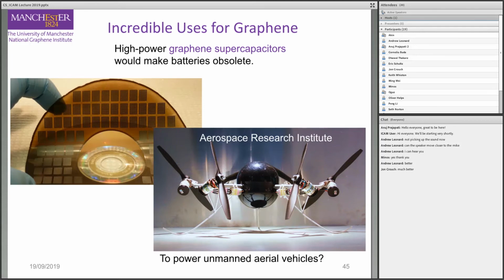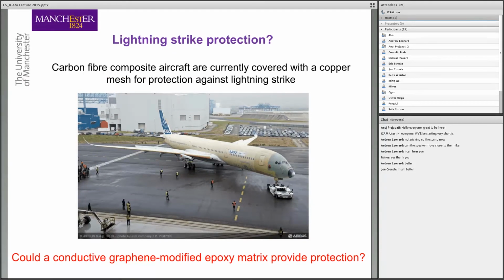And then we go back to those composite airframes like the Airbus A350 and the Boeing 787. Those structures, those carbon fiber composite aircrafts, are currently covered with a copper mesh for protection against lightning strike. Which, of course, by adding this additional load, you take away the advantages that carbon fiber systems offer us in the first place. And the question is, could a conductive graphene modified epoxy matrix provide protection? Can we provide that protection during the spraying, the paint, when we paint the aircraft, and we have the graphene nanoplatelets that make the whole thing electrically conductive?